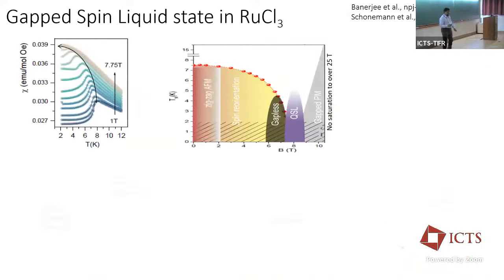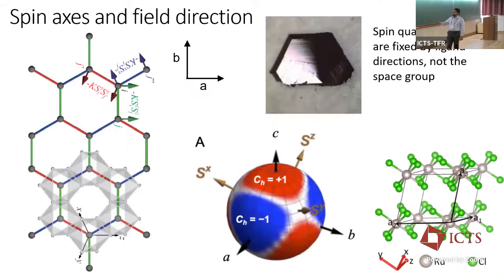With that understanding, it was easy for us to apply the field in an in-plane direction, which, mind you, is not along one of the spin quantization axis directions. We applied a field in the direction where you should get a Chern number equal to minus one. That's the A axis. What you also find is that along the B axis, the Chern number is zero, which means you should expect gapless states there, and you should expect gapped states if you apply a field in the middle of these red and blue regimes in this material.